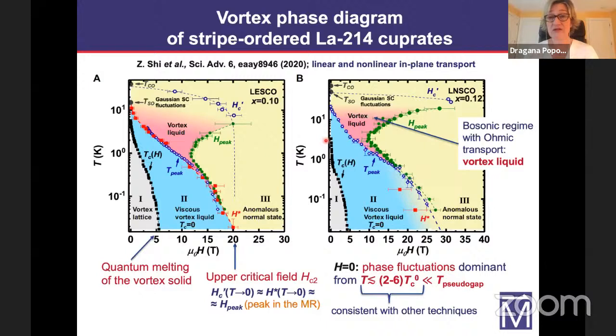Also, at zero field, what we see is that the onset of phase fluctuations is at temperatures that are several times higher than Tc. And this is actually consistent with the findings of many other experiments using spectroscopic techniques, also on other families of cuprates. However, in these two materials, this is still a temperature that is much lower than the pseudogap temperature. So at least in these measurements, we do not see evidence for pairing at temperatures that are comparable to the pseudogap temperature. There are a couple of other things that I would like to point out.